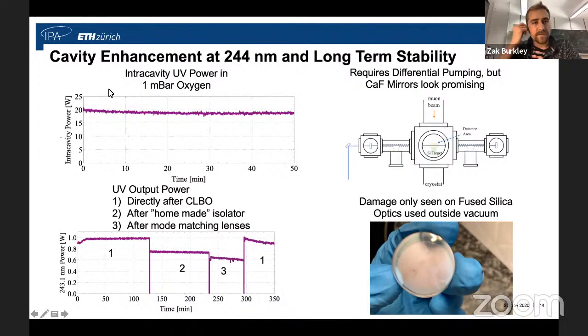So here I have a picture of our intracavity UV power, and we have this in some oxygen. And this is at 20 watts, and we see it stable for about an hour. Being in oxygen, this requires some differential pumping, which we are able to implement by restricting the cavity to this 3mm aperture all the way through the vacuum system. And inside the center part is our spectroscopy chamber.